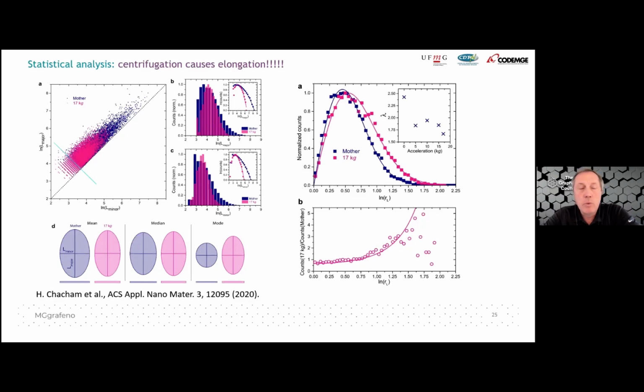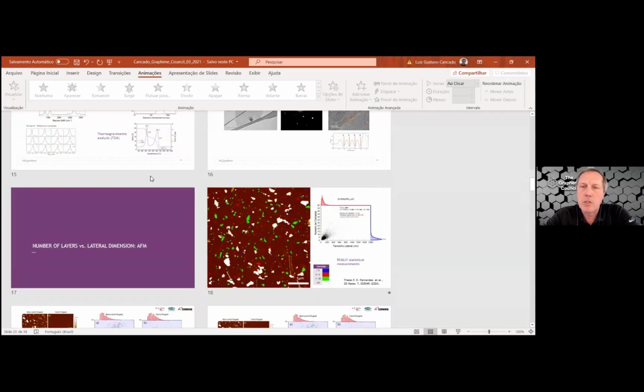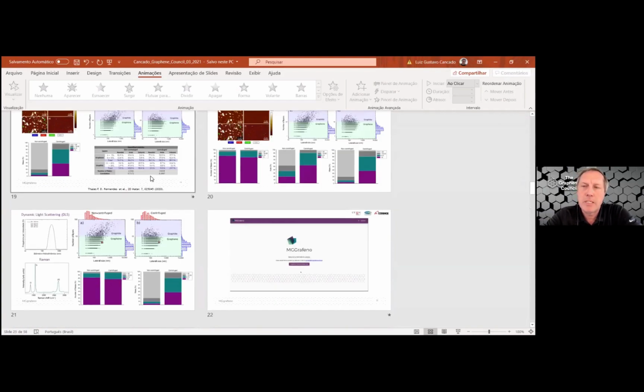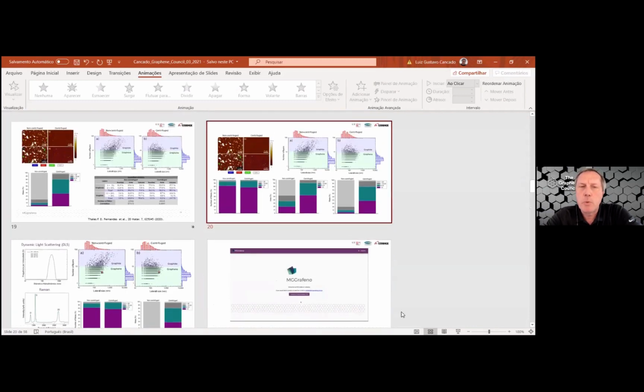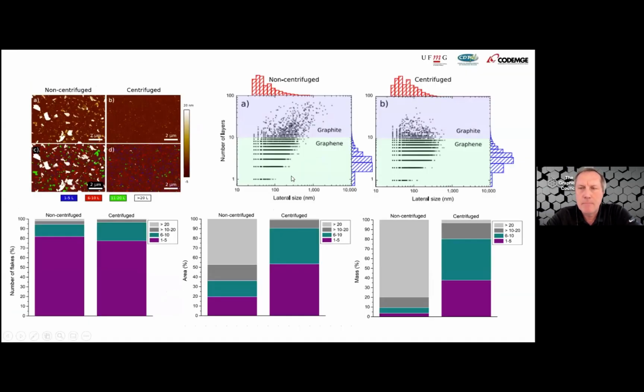But I found it really fascinating. We have big problems with specification sheets for material. We're talking now from the commercialization aspect. People claim, okay, our material is 6 to 9 layer graphene material, but they don't give a distribution. They don't say what percentage of flakes are sub 6, how many are between 6 and 9, how many are above 10, for example. And what I found really fascinating, exactly on the slide you have up here, was the difference between a statistical number based on flake size, then the difference based on area, and then based on mass.